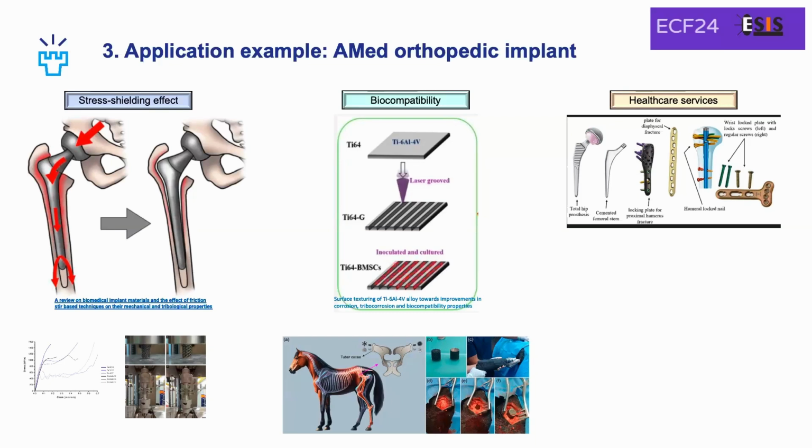And we hope that in the future we don't have titanium here. We take something like magnesium that will be dissolved by the body. So then it will be more or less an optimization: if the body grows into the implant and the implant has some fatigue strength and some reliability, they should go hand in hand so that the implant wouldn't break before the bone has grown through. But we are not there yet. This is the idea for the future.